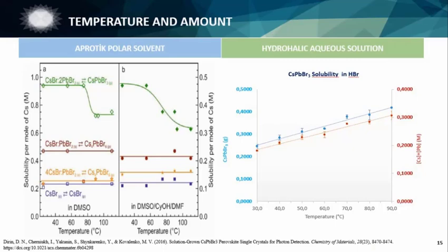Thermodynamically speaking, single crystal formation and growth are promoted in a narrow solute concentration area at a specific temperature. For this reason, solubility plots were created for cesium lead bromide crystals in hydrobromic acid. By determining the required amount of precursor at a specific temperature, the formation of multiple nuclei and polycrystals was avoided. In this work, precursor solutions were prepared for a particular working temperature in order to redissolve any accidental nuclei formation.